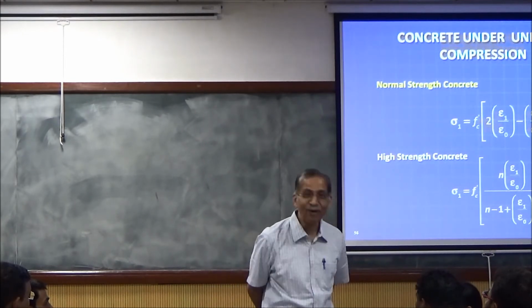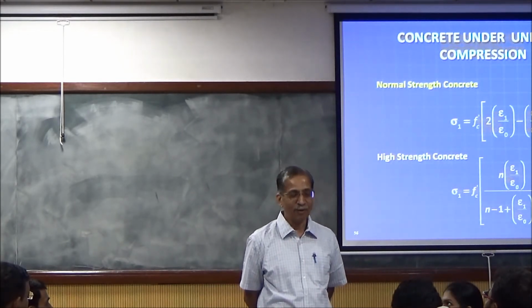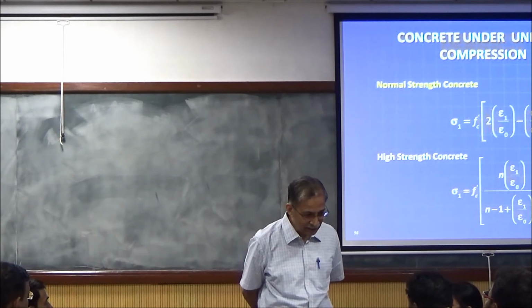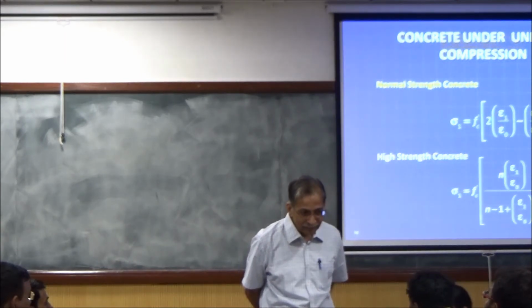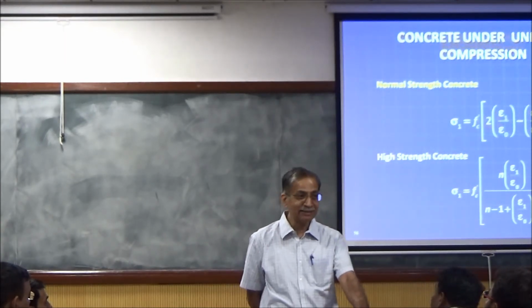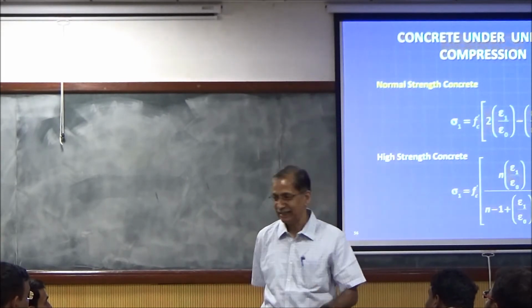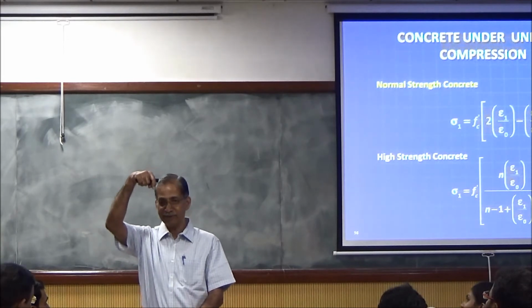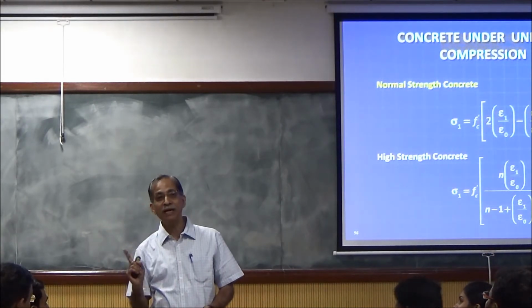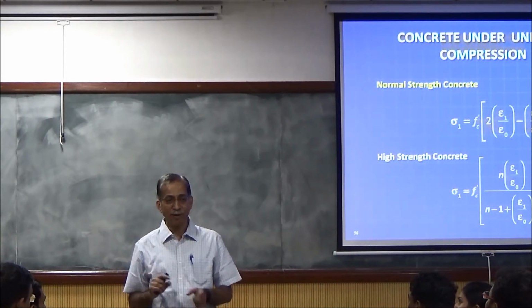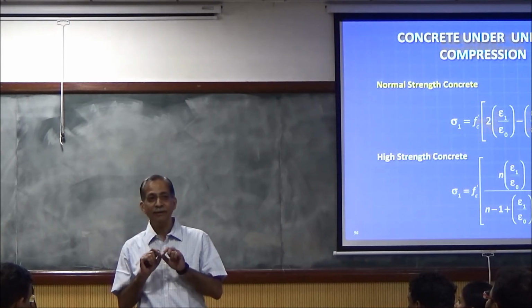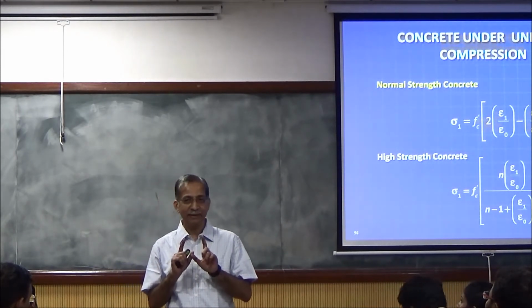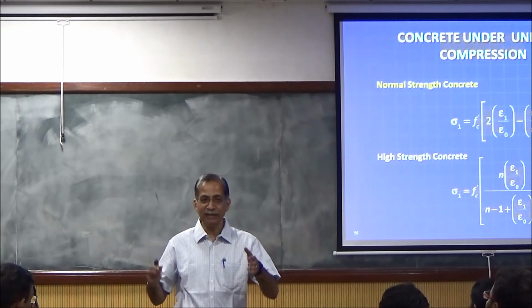Poisson's effect, correct. What is Poisson's effect? Will I get a tensile stress? Strain. So I have axial compression, I am applying a load, I get axial compression strain, I get a hoop tensile strain, and concrete is weak in tension, it will split in many places.